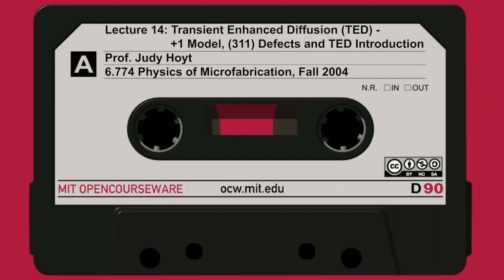It looks like a hopping frequency times a Boltzmann factor, e to the minus E_B over kT, where E_B is the binding energy. So again, if I'm going to get rid of an interstitial from the cluster, it's going to be bound by some energy. Somehow there's a lower energy to be in the cluster. I have to overcome that to get rid of it, and that's why you have this e to the minus E_B over kT. So a simple differential equation with two rate constants, k_F and k_R, that have certain temperature dependencies.